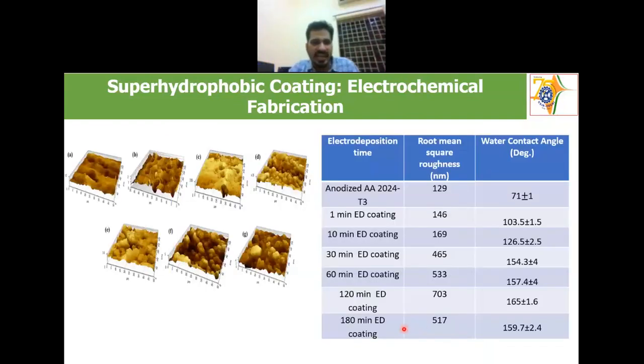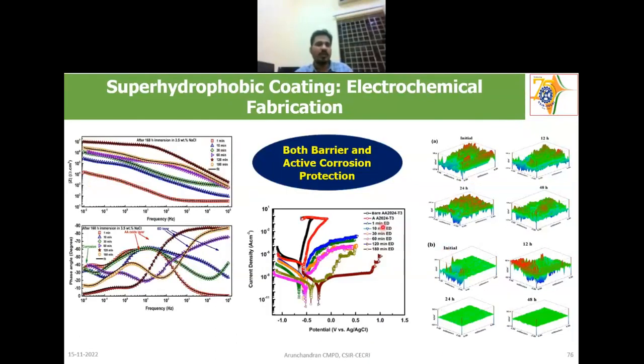And this is the AFM image of that type of coating deposited at various time intervals. As you can see, the contact angle is increasing, the electrodeposition time is increasing, and the roughness is also increasing. We did corrosion studies also for these coatings, and I will explain this part, especially the SVET part.